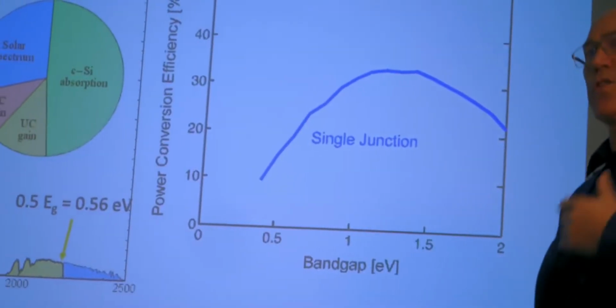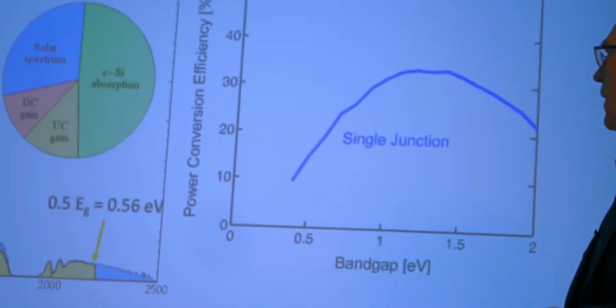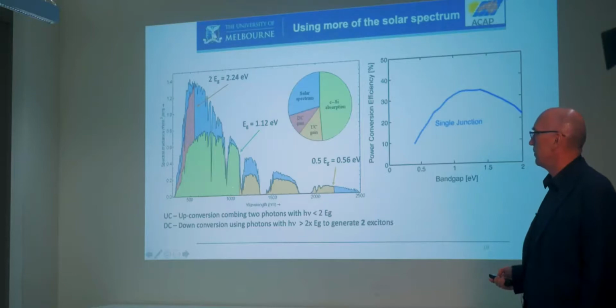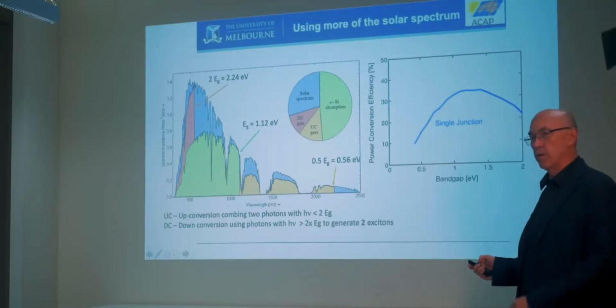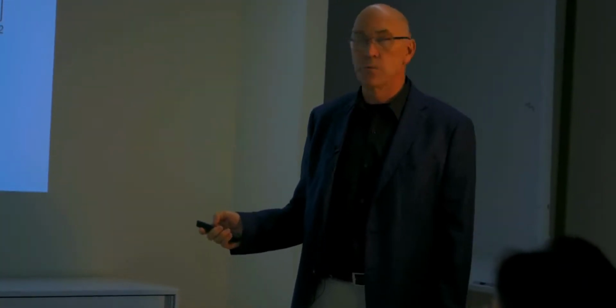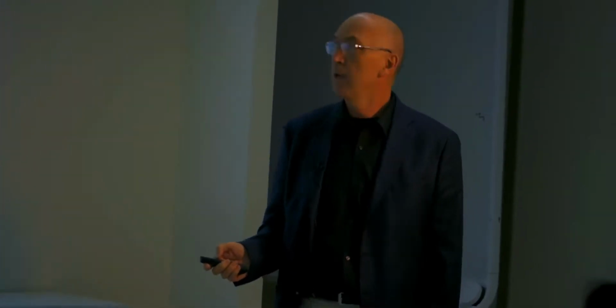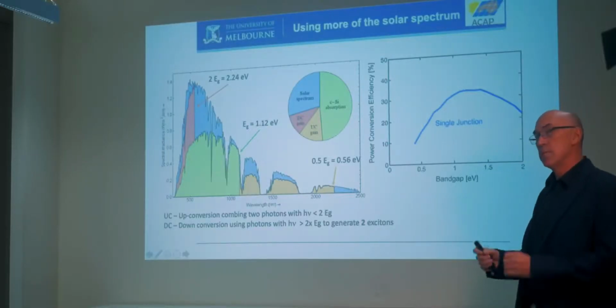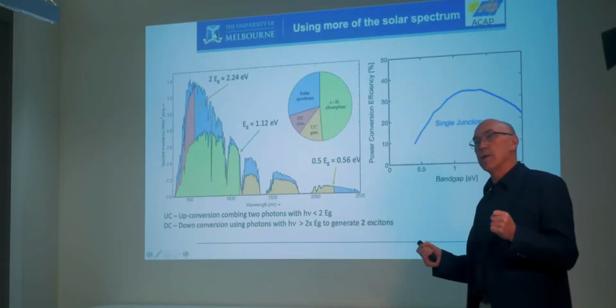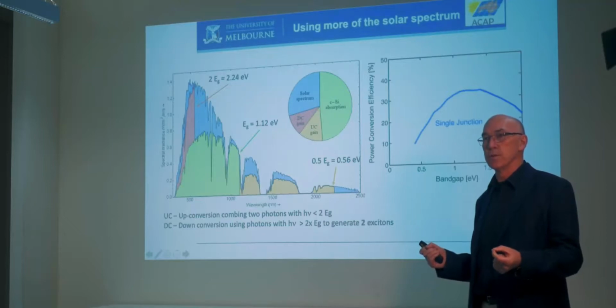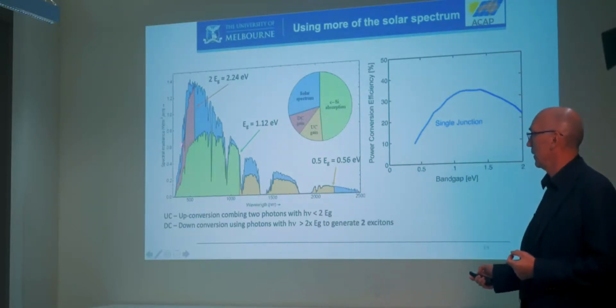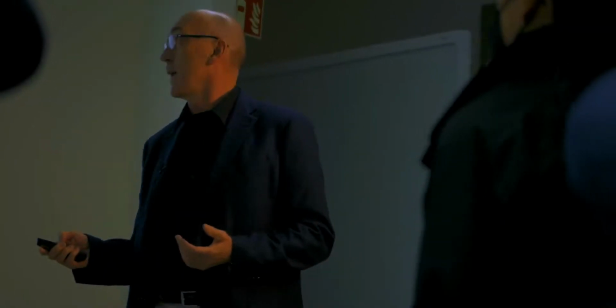And so we can do things called up conversion, down conversion. Okay. And so if you look at these photons below the band gap of silicon, if you can combine the energy of 2 of these, i.e. up conversion, you can generate a photon or an excited state in the silicon, which you can then use to improve the efficiency of the silicon. Equally, if you have a photon which is twice the band gap, maybe you can make 2 excited states out of it, and therefore you can get 2 charges per photon, and therefore increase the efficiency up here. If you look at the theory of that, you can take a 33% efficient solar cell, this is theoretical maximum efficiency, and you can go up to 45.